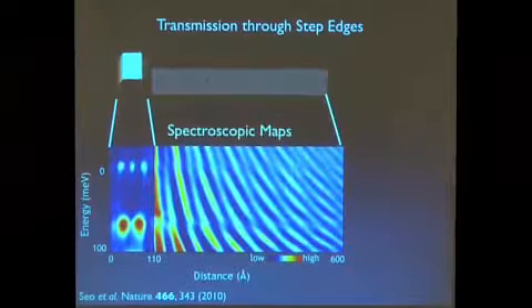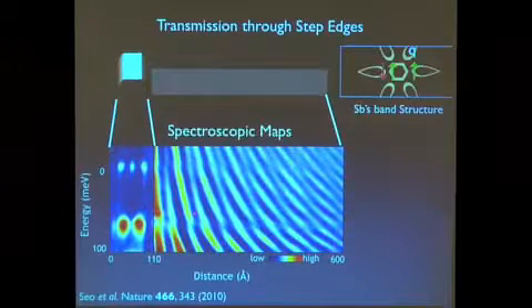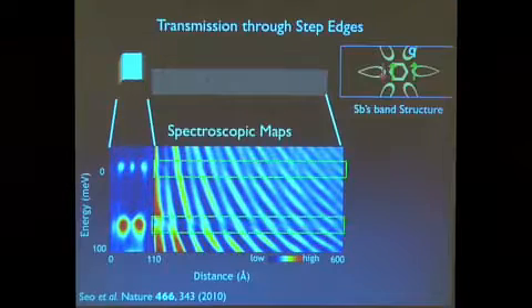The question for us was that we had done experiments like this on ordinary surface states. We always saw that there's basically no transmission through this small terrace. Okay? This is kind of like a Fabry-Perot interferometer. And if you look very carefully, there is a slight difference between ordinary electrons and antimony, because they are topological, the standing waves you see are made not of K and minus K, but of K and K prime, where they have the same spin structure in the sample. Okay? So what you see here, if you focus in on the data, is energy, and the colors represent the square of the electronic state, as a function of how many electronic states you have at a particular energy as a function of position.